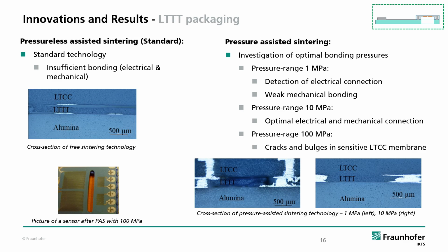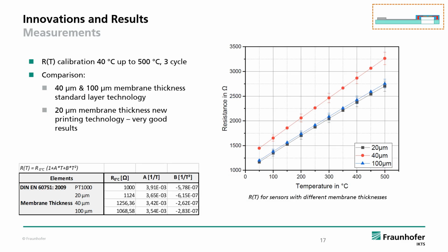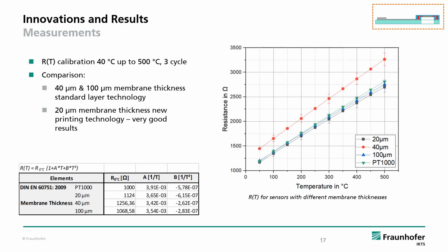So after finding the optimal process parameters, it is possible to measure the sensors. We started with a resistance over the temperature curve with the different membrane thicknesses up to 500 degrees. Here you can see the results compared to the PT1000 curve. So 20 micron membrane thicknesses and 100 micron show an excellent fit to the curve. On the other hand, 40 micron membranes has a much higher drift. The reason can only be found in the different fabrication process, since all materials are the same in all processes. And as you can see in the diagram, the printed membrane shows very good results.